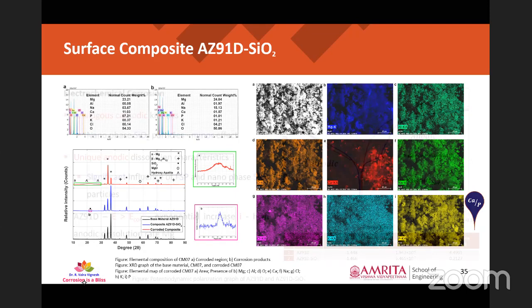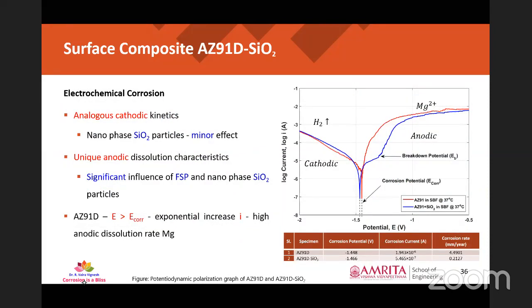Yes, and coming towards electrochemical corrosion characteristics, we'll just compare the base material and the composite one. So the red colored line is the potentiodynamic polarization curve of the base material AZ91D, and the blue colored line is the potentiodynamic polarization curve of the composite material. So speaking about the cathodic characteristics, the base material's cathodic kinetics and the composite's cathodic kinetics are very much analogous. It is very much similar. So it means that there is minor influence of nanophase silica particles on the cathodic kinetics of the material. However, when we look at the anodic dissolution characteristics, there is a significant difference between the base material and the composite that we have developed.